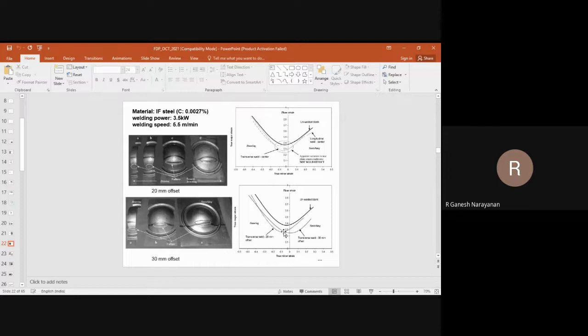And you will see the bottommost figure, I will explain first. The black one is the unwelded sheet. And the dotted ones: first one is transverse weld 20 mm offset, then transverse weld 30 mm offset. And you will see the 30 mm offset has got slightly lower formability as compared to the other two, which means the location of weld is also important.